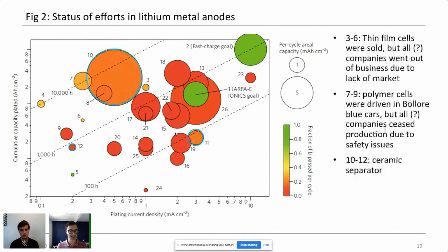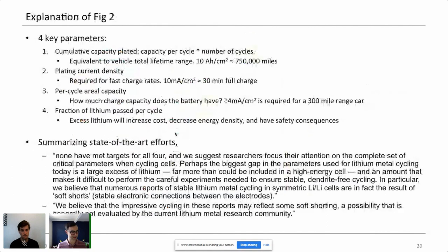So one of the big contributions of this paper is that they highlighted that and are encouraging the research community to be aware of it. What they say later in the paper is, we believe that the impressive cycling in these reports may reflect some soft shorting, which means dendrite formation, a possibility that is generally not evaluated by the current lithium metal research community. So they're basically calling out some folks who are not aware that the performance they were claiming was actually far from being a record result demonstrating safety or efficacy of their battery; they were actually showing that their cells had already failed. So it's something that I know to be the case. I personally know that there are published reports out there that claim that they have excellent performance from their battery when what they're measuring is a failed battery.